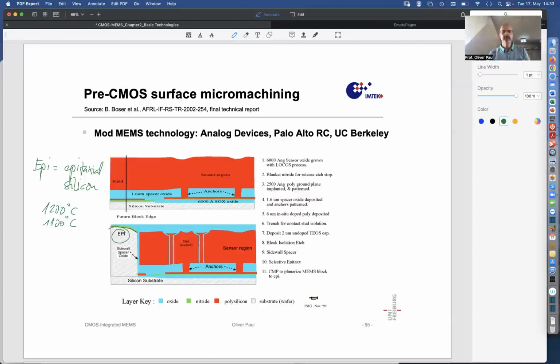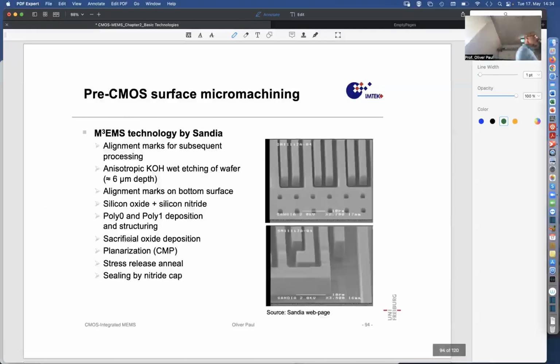So it looks like here, oh, there's my pen. Here, so there was a sensor oxide grown, and then nitride, and then poly, a blanket poly here, and then some additional spacer oxide, and then more silicon, and then the epi growth, and then more planarization, and then the whole thing is basically ready to receive some CMOS. And then once the CMOS is done, you can remove the blue area if you want, the light blue area. And that releases a structure to produce something which looks like that, released silicon, mechanically mobile silicon.